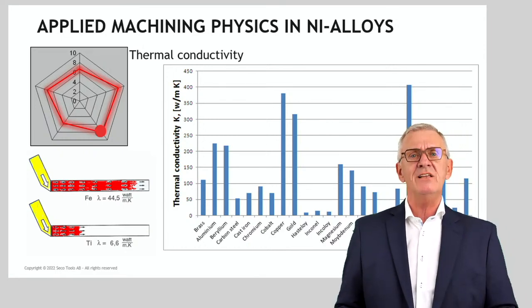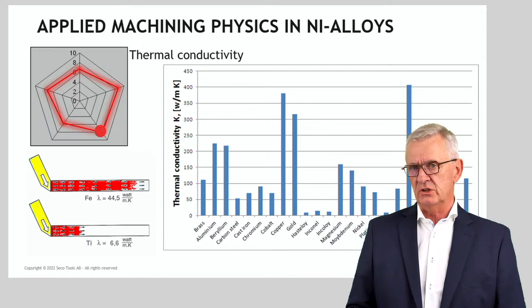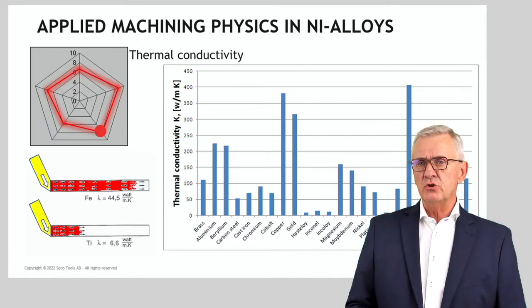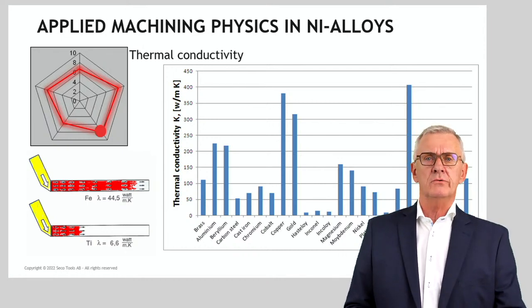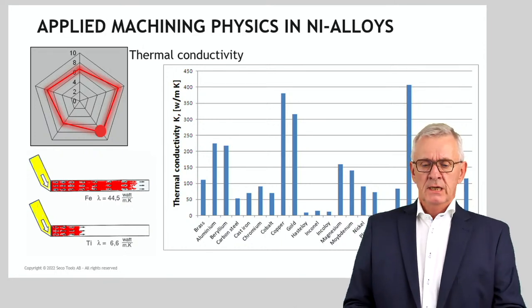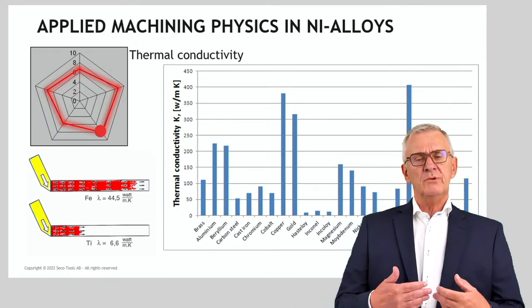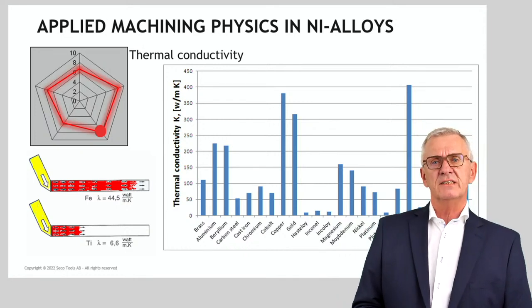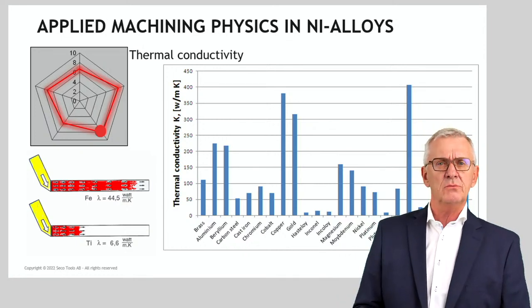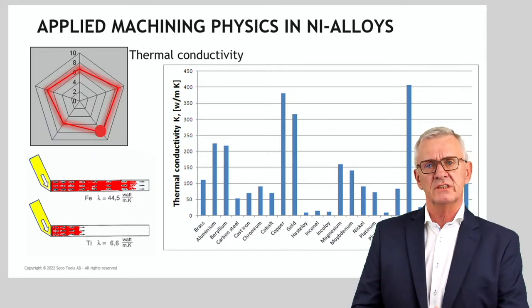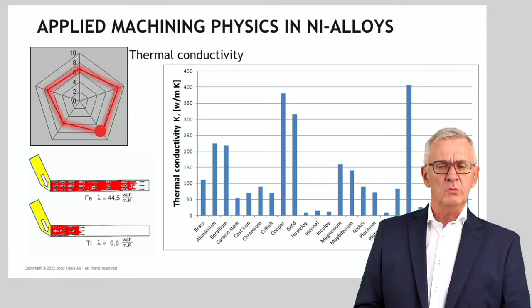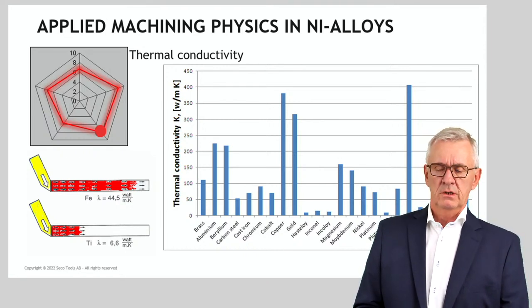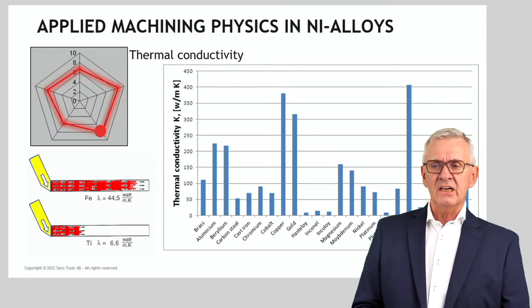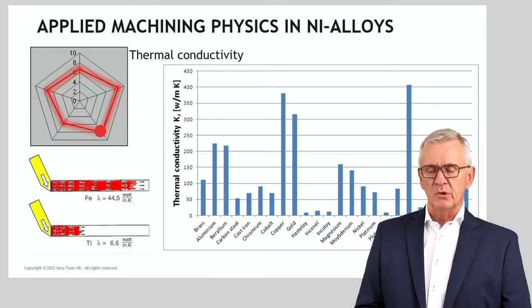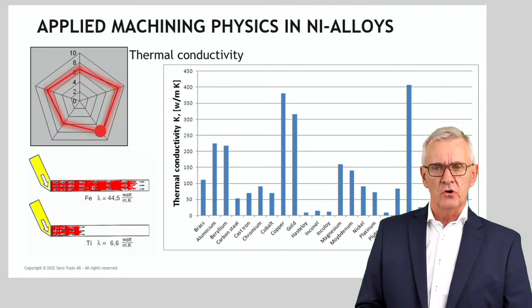Now, what does that mean? It means that if you do machining, heat is generated. And that heat needs to be evacuated away from the cutting zone. Otherwise, it would lead to a higher cutting temperature, which is a problem, because it will deteriorate the cutting capacity of your cutting edge. So we don't like high temperatures. We don't like concentrated heat in cutting zones. And in normal machining, we count on the heat being evacuated with the chips. And in normal, let me say, iron materials, that's rather easy because traditional iron has a rather high thermal conductivity.